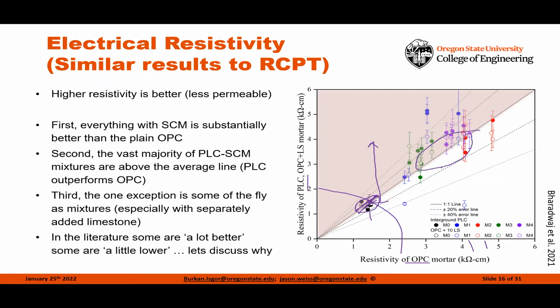So we see, first of all, that they move from a value that's down here to a value that's almost triple. In addition to this, what we start to see is that the limestone in these systems starts to see a little bit of an improvement off that line of parity. So we see the PLC itself is about 20 to 30% more beneficial in these systems, because partially of that reaction with the alumina phases.